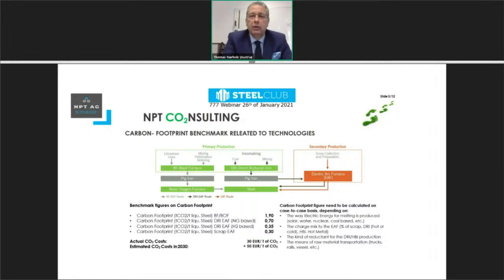And all of this, for sure, depends on the way the electric energy is produced, whether it's done by solar, water, nuclear, or coal-based power. It depends on the charge mix which we can feed to the EAF. We have a tool for melting which is extremely flexible, which can use scrap, DRI, either hot or cold, HBI or hot metal. If still in existing traditional steel plants we have an overcapacity for a certain while of hot metal, the reductant which is used in the DRI and HBI production, and also the means of transportation, how we transport the raw materials into the plant, are aspects of this calculation of CO2 footprint.